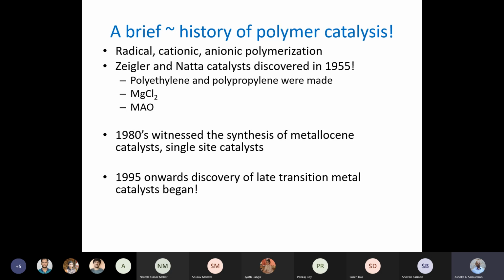One of the important modifications is the fact that the catalysts are titanium or zirconium. They are supported, there's a better word, they are supported on magnesium chloride. And people have found that if you use MAO again, you will get fantastic results, meaning that the catalyst loading that you use per gram of polyethylene is minuscule. In fact, the catalyst is never recovered in these reactions because the turnover number is so very large. So people never recover the catalyst.